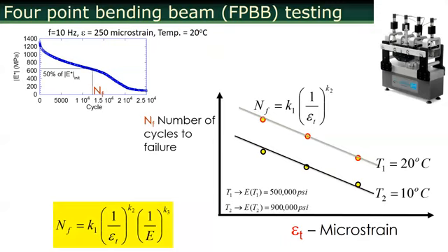Now, a situation where you have a third set of data. If you run another set of data at, let's say, a higher temperature, you can still calibrate the same model, and we do that actually, because for the third set of data, 1 over E will be different. So E essentially is your another input. So this is x, this is y, and this is z.